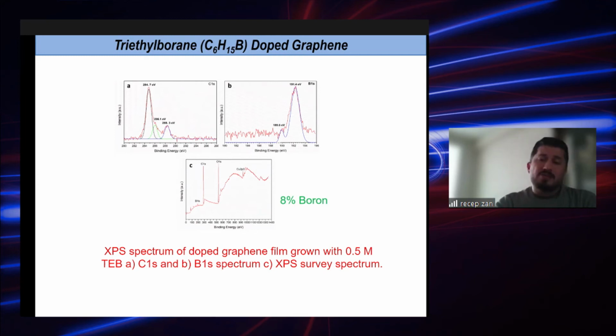In our case, when we grow graphene with 0.5 molarity TEB, or triethyl boron, we find 8% boron in the structure. But another important thing to emphasize here is that this is the most homogeneous and the highest boron content graphene synthesized up to now.